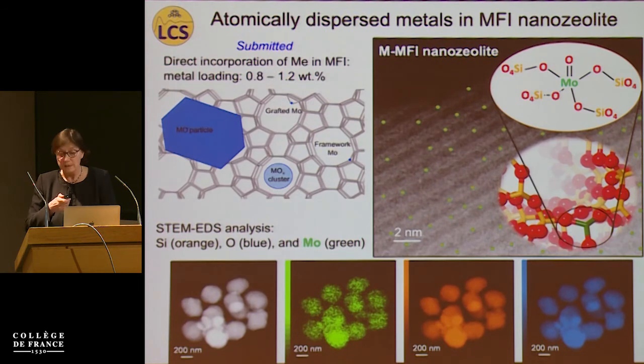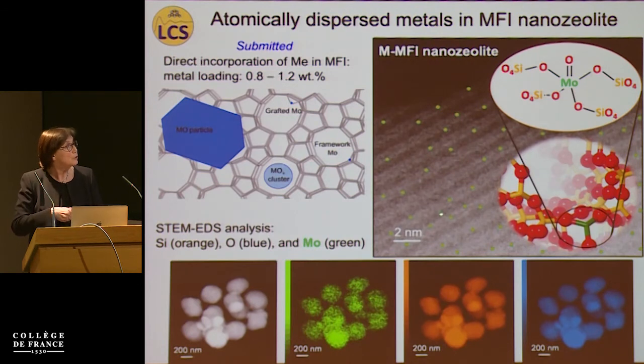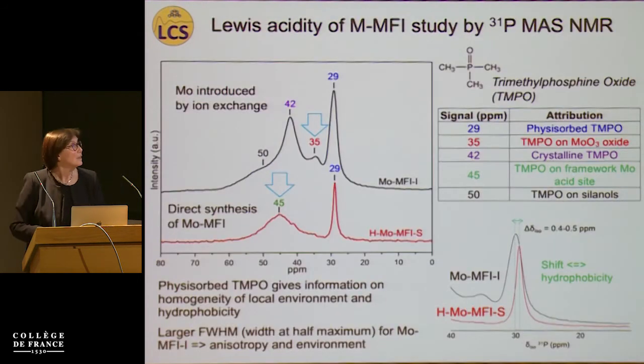Very recently, we also succeeded in the preparation of atomically dispersed molybdenum within MFI nanozeolite, and we prove that this molybdenum is located in the framework in tetrahedral position, and again, this material is silanol-free. In order to understand whether we have a homogeneous distribution of this molybdenum in the structure, we also performed phosphorus NMR, where as a probe molecule we use trimethylphosphine oxide, and we were very happy to see a peak at 45, which corresponds to TMPO on the framework molybdenum acid sites.